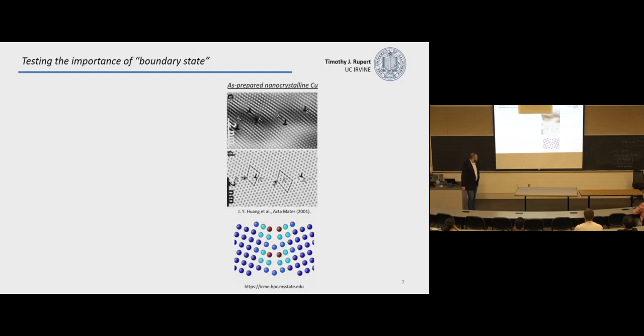So I wanted to take a step back and think about how grain boundary structure might affect mechanical behavior. And I'm going to start by talking for a second about how we make these materials. We often either smash them together, put a lot of mechanical energy into them, or deposit them very quickly so they get stuck in these small crystals. And when we do that, we often have extra disorder at the grain boundary. What's shown here, this top one is a micrograph of a grain boundary along this middle plane in a nanocrystalline copper.